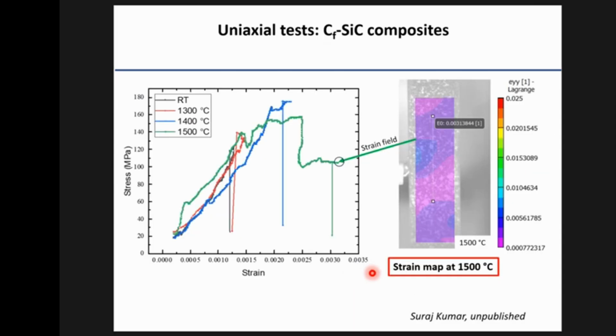And I'll show you an example of a test. This is now a mechanical test using this digital extensometer, if you like, the DIC as an extensometer. So we're not measuring spatially resolved strain here, like in bending. We're just looking at the pattern between the top and the bottom of the gauge length. And in fact, one of the things that allows us to do is to take smaller gauge lengths, because you don't get uniform temperature,